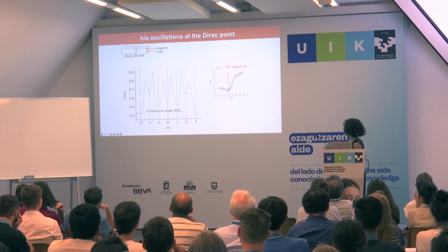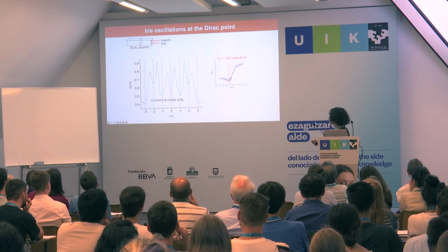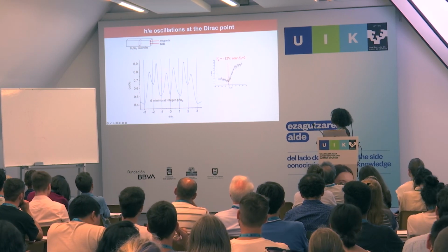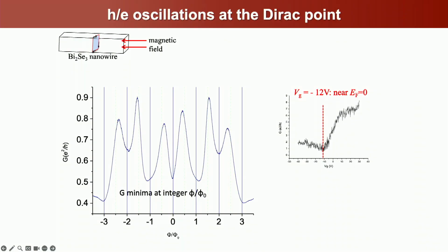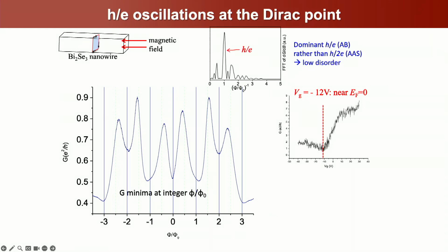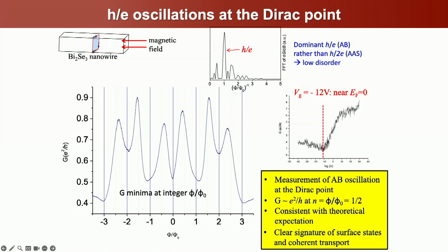Okay, so to cut to the chase, we measure conductance. We see these Aharonov-Bohm oscillations. They have amplitudes that are close to e squared over h. They're very clearly h over e oscillations, and as I mentioned, you can take a Fourier transform, see they're h over e, not h over 2e, which would be a disordered case of oscillations. And overall, just from seeing this alone, if you tried to measure Aharonov-Bohm oscillations in just a strip of metal, you would see almost nothing, or you'd see nothing. Okay? And you'd see nothing because you don't have a well-defined phase coherent path around this.